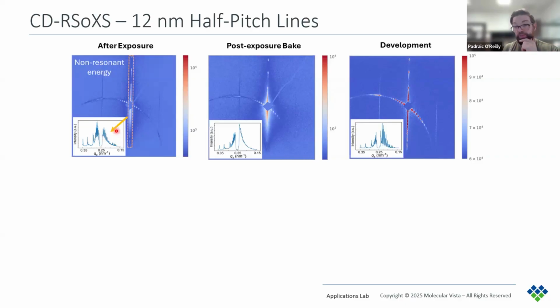So we see that the after exposure sample and the developed samples both show a strong scattering pattern, while the post-exposure bake does not. Now this matches what we've seen with the topography images during PiFM for the post-exposure bake and the SEM images on the developed sample, that after exposure and developed samples showed a clear topography pattern, but the post-exposure bake did not.